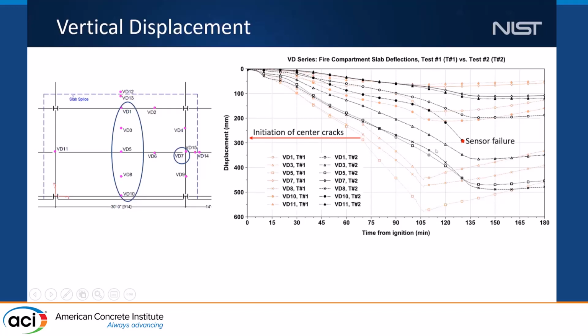However, in test number 2, the vertical displacement increased in a more gradual fashion, but it went all the way up to 50 centimeters. This is equivalent to more than probably the L/20 ratio, the span length over 20 ratio that is permitted and used for standard fire testing. So it's a very large vertical displacement, but there's really nothing happening for that.